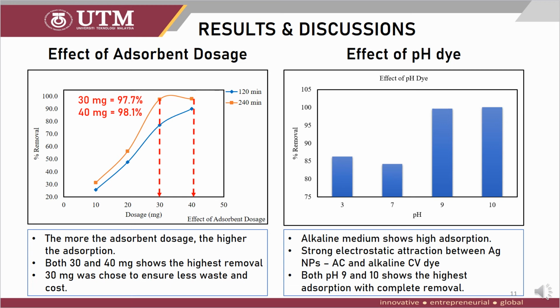The next parameter is the effect of dye pH. As you can see here in this figure, alkaline medium shows higher adsorption compared to neutral and also acidic medium. It is because of strong electrostatic attraction between AgNP-AC and the alkaline CV dye, and both pH 9 and 10 show the highest adsorption with complete removal of this crystal violet dye.